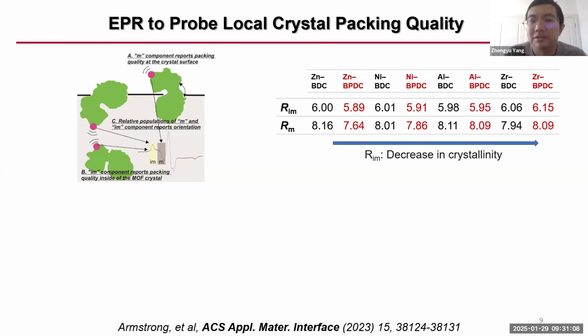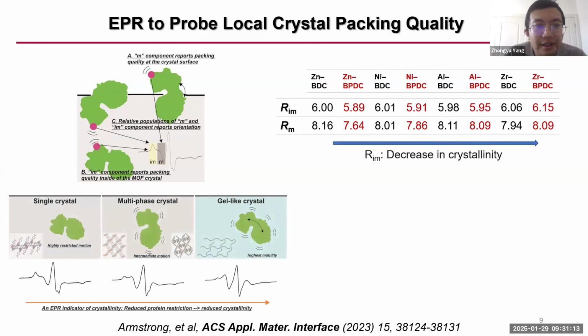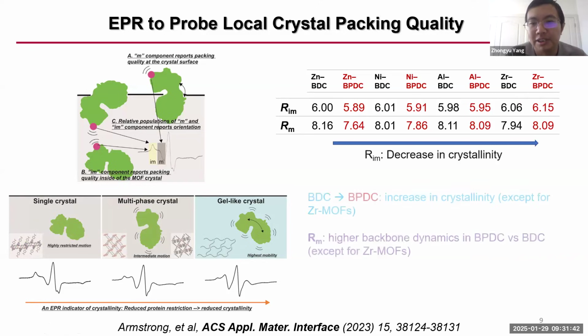Meaning, the lower the rate, the slower the motion, right? And then, this is what we propose, a single crystal sharp, right, multi-phase, right, that's the real data. At the very end, you can see there is a jump, especially the BPDC, there is a jump in the motion, in the R rate constant, and that is because when it's not crystal, and it's still solid, it feels like a gel. So when there's a gel, you have the highest rate.